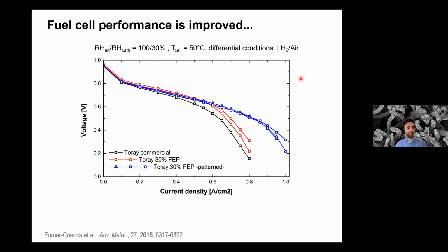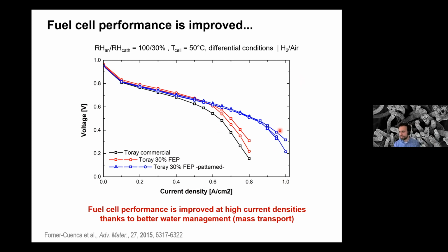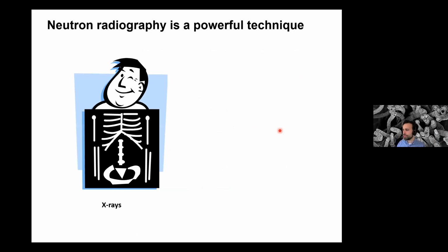So like I said before, polarization curves at different conditions. And what we see is that comparing the blue, which is the modified material, with the red, we were able to see that the mass transfer overpotential is lower in the case of materials with pattern wettability. And so we attributed these improvements in performance due to a better water management. And we did a lot of Neutron work to learn where the water was going in operando. And this is what I'm trying to explain here.